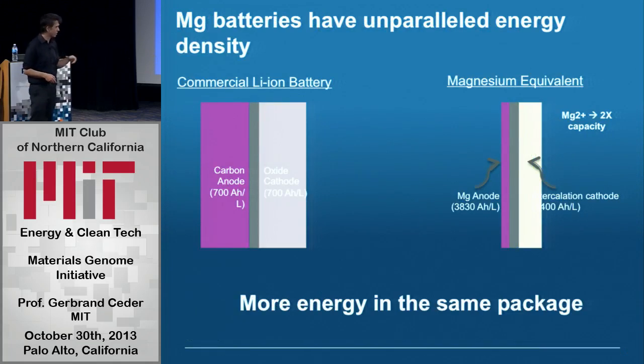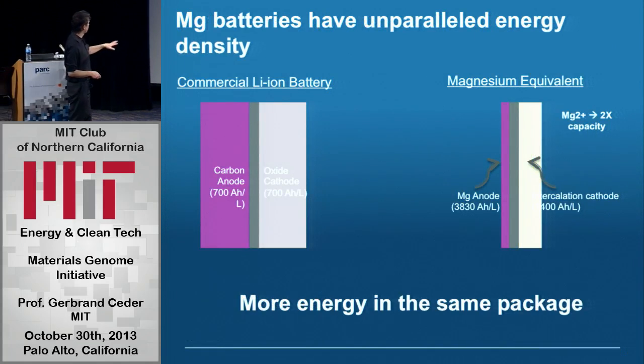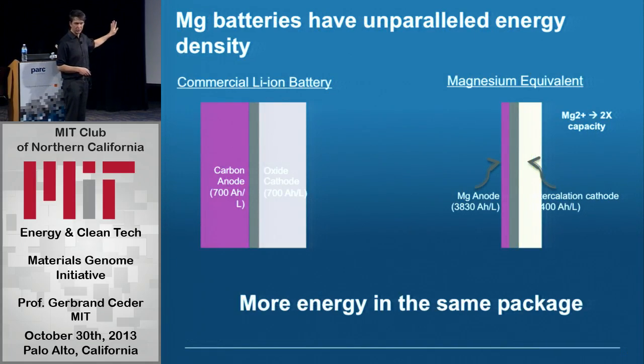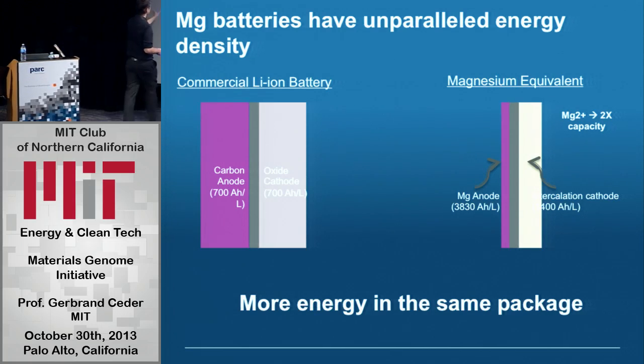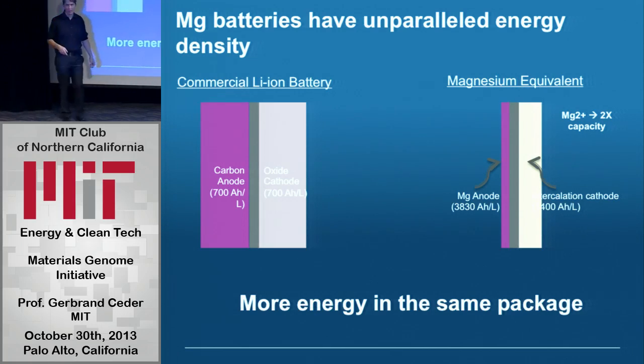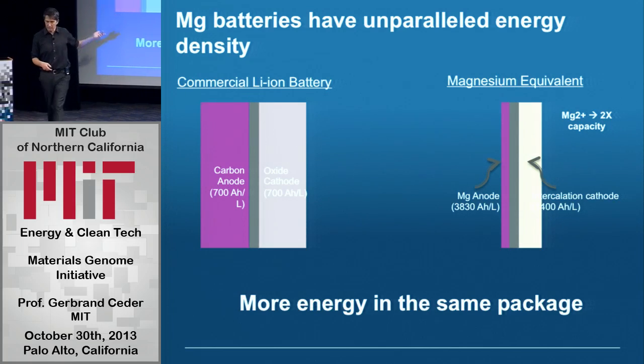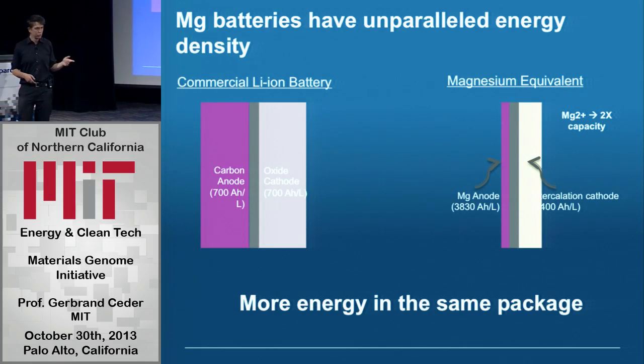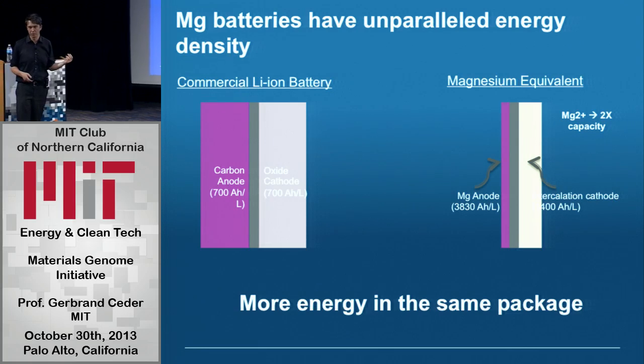And here's a comparison slide. If you take a picture of a commercial lithium-ion battery, with the thickness of the anode layer and the cathode layer, and you make the same comparative thickness on a magnesium battery, you see that you end up with much thinner layers. So this is mainly a technology for extremely high volumetric energy density.